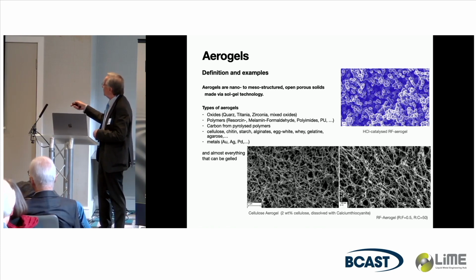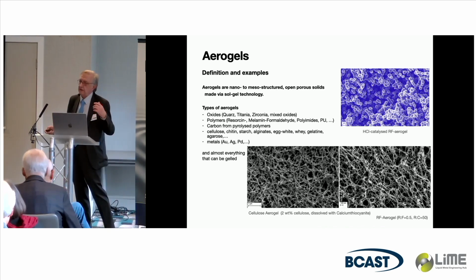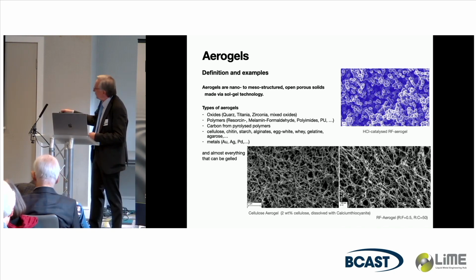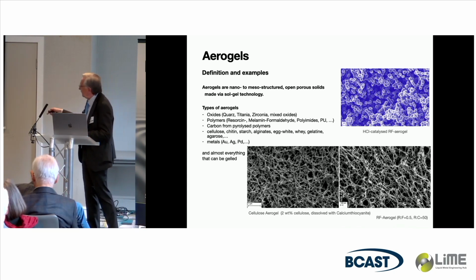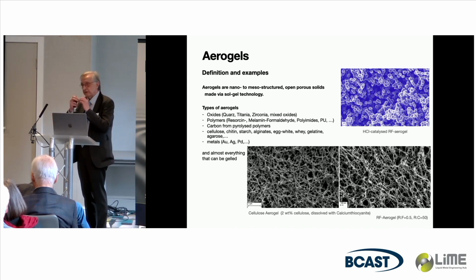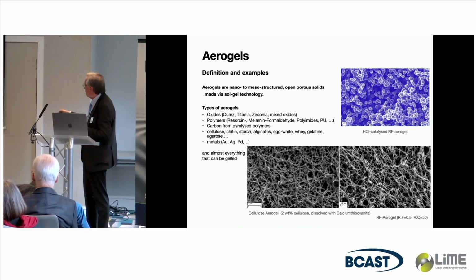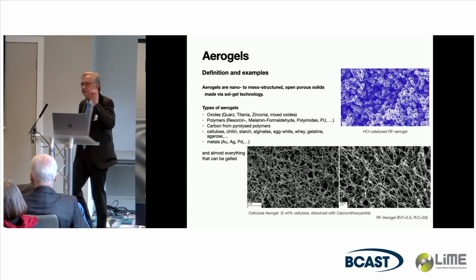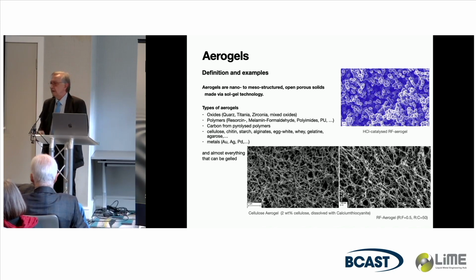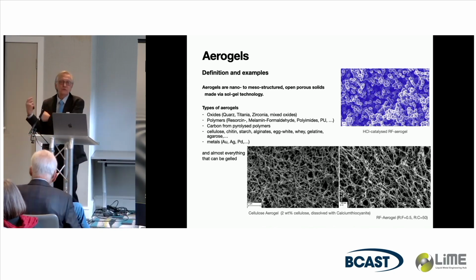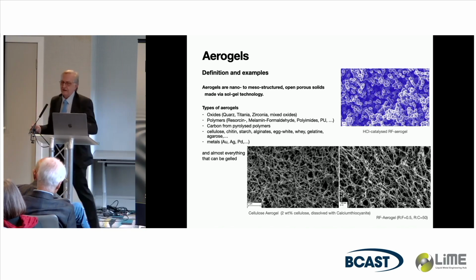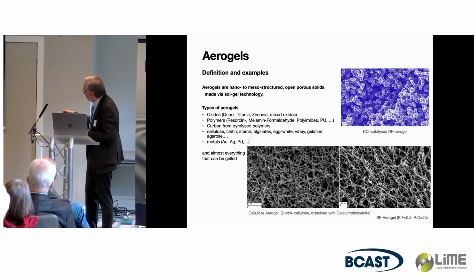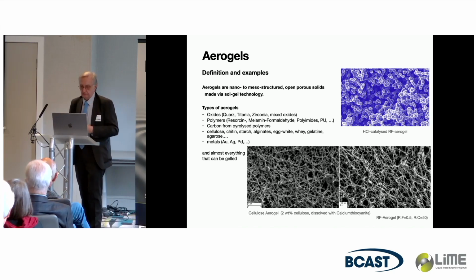This is resorcinol formaldehyde, nicely spherical particles. Size is typically around a micrometer. It looks like a Hollywood spiderweb in nano size. And if you do that with cellulose, you also have a wonderful spiderweb. These are really nanofibrils, 10 to 20 nanometers in diameter. If you look much closer, which is not easy because these polymers have no electrical conductivity, doing scanning electron micrographs is not that nice. But it works. You see these are in reality small strings of pearls.